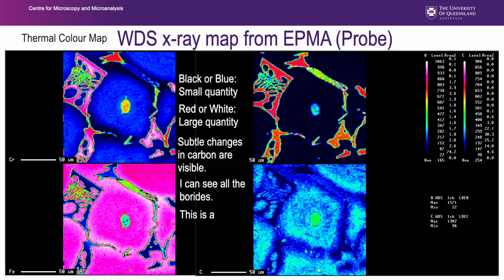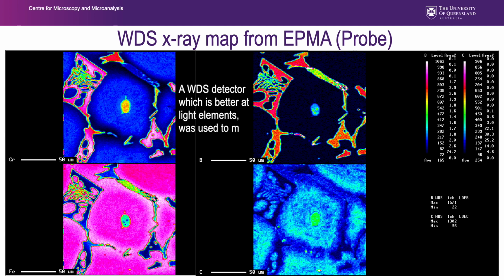This is a high alloy steel. And there's actually a lot of subtlety to that map and changes I can pick up. It's a good quality map. It did use a WDS detector, which is better at light elements. And that map took me 48 hours to map, 2 solid days. 24 hours mapping on the peak, followed by another 24 hours mapping off the peak. You've got to do that separately with WDS to do a peak above background subtraction.